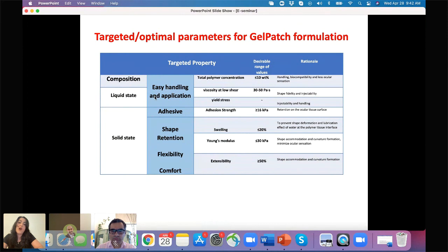Basically, for the pre-polymer solution, our goal was to engineer a formulation that can easily apply, and it has a proper viscosity that we can inject it. So therefore, we look into how we can optimize the composition of the hydrogel and how should be the rheological properties of this material. And once the hydrogel solidify after photopolymerization, it's important to have enough adhesion strength so it can retain on the ocular surfaces.